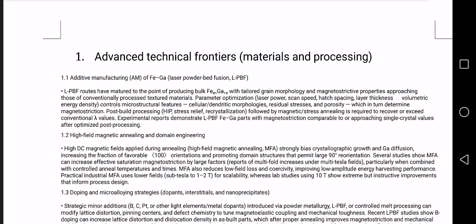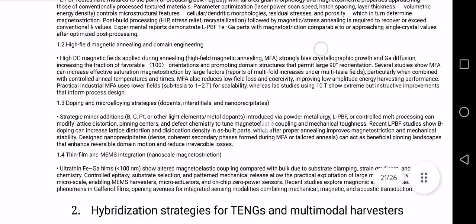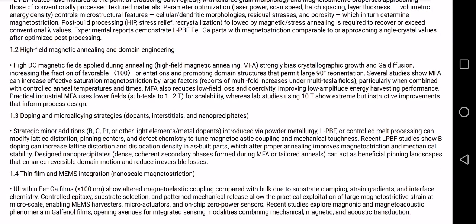Now, next we have high-field magnetic annealing. Let us talk about magnetic field annealing. In magnetic field annealing, we anneal FeGa while applying a strong DC magnetic field. This biases crystal growth, aligns favorable 100 orientations, and promotes easy 90-degree domain rotation. Research shows that magnetostriction can increase by multiple times, coercivity decreases, and low field efficiency improves.